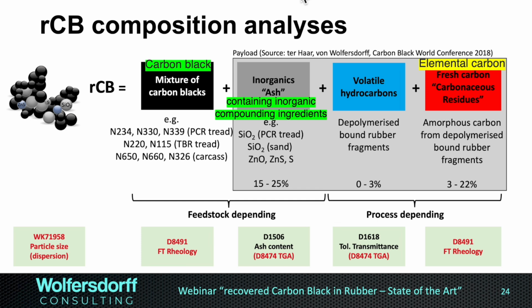And then we have only one missing factor, and that is a recovered carbon black put into the rubber cannot do its work if it is poorly dispersed. And the dispersion really is a very good correlation with the milling and the particle size of the recovered carbon black. The finer we mill, the better is the dispersion in a rubber compounding.